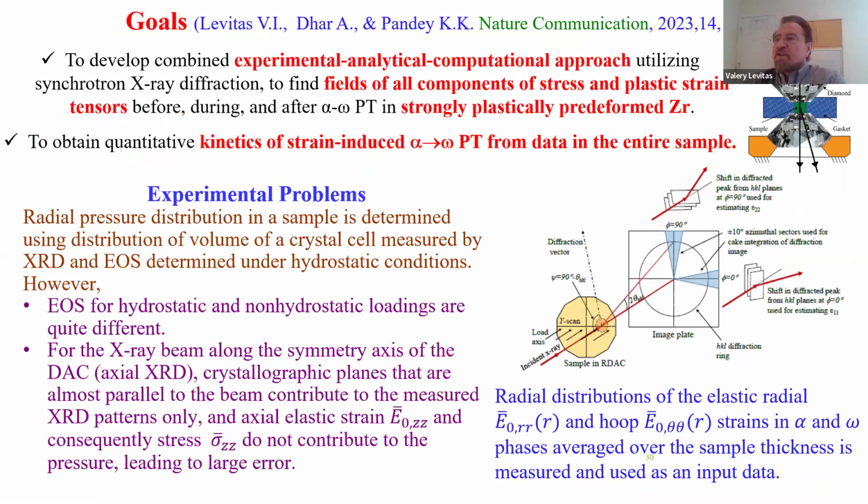Okay, to develop science, it's not sufficient to talk about stress and strain tensor. We need to know them, but they are not measurable. So that is why we develop combined experimental-computational approaches, in which we develop a macroscale model with unknown material properties. We produce simulations, determine all fields, and fit them to what we can measure. And from this fitting, we determine unknown material properties, and also all tensorial fields.